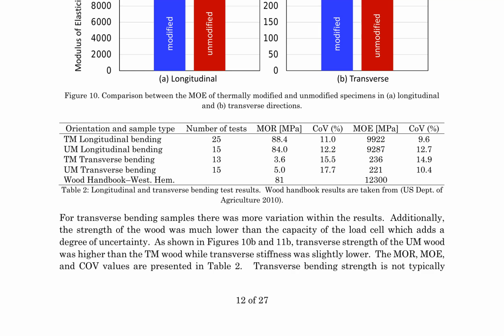Comparison of MOE values in longitudinal and transverse directions, Figure 10, showed higher MOE values for TM wood in the longitudinal direction and lower MOE values in the transverse direction. Longitudinal and transverse bending test results, including MOR, MOE, and COV values for TM and unmodified wood, as well as Wood Handbook values for Western hemlock, are presented in Table 2. Notably, transverse bending test results showed more variation and lower strength, with values below the capacity of the load cell, adding uncertainty to the results.